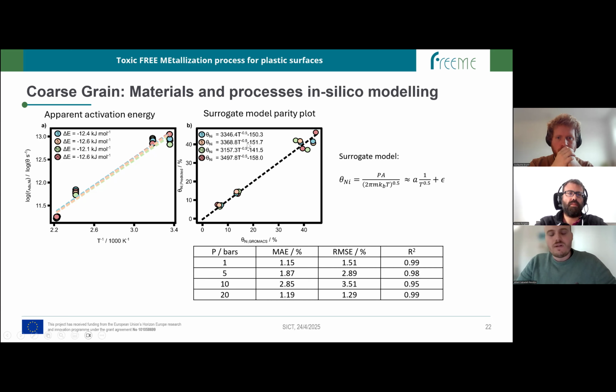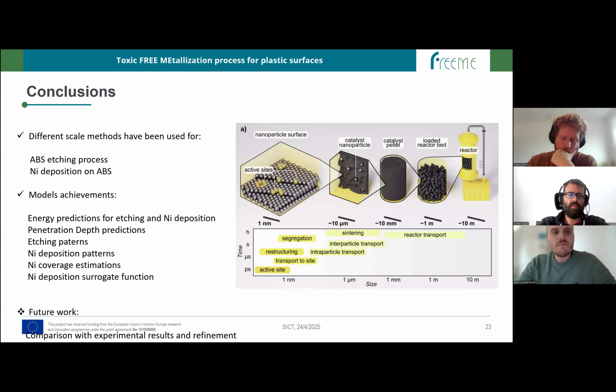And with that, we can develop a surrogate model that will come directly from adapting the typical Hertz-Knudsen equation for adsorption of gases on surfaces, assuming that nickel would have a similar behavior. And actually, it works pretty well, I have to say. This can be used as a surrogate model that we can then plug into higher scale models, such as CFD simulations, in order to have a more one-to-one comparison with the real experiments.